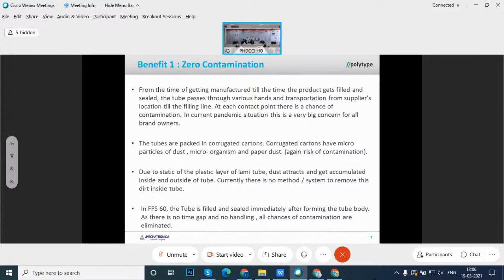Okay, as you see here, from the time when you start making the tube to the moment when you fill this tube, it goes through different stages and also usually two different places when we use standard technology. First the tube is manufactured somewhere, then it's packed, usually in cartons. Those cartons can also create some contamination because they are not perfectly clean. Sometimes they are wrapped in polyethylene bags, but this process takes time. So there is always the risk of some contamination from the cartons.